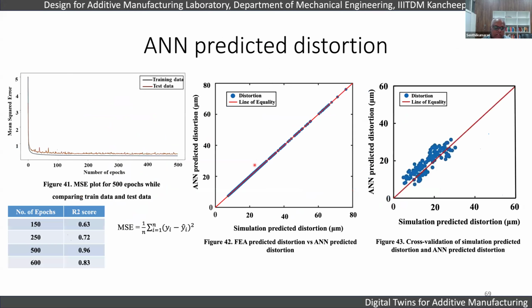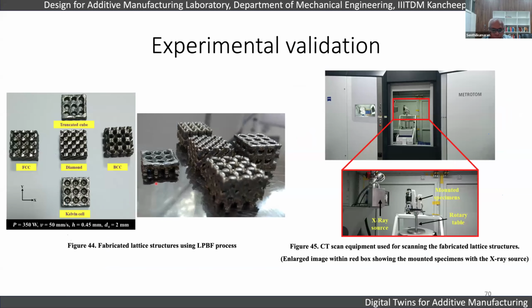You can see that we can get an R square value of as high as 0.96, and we trained for 500 epochs. Then we did an experimental validation with the Inconel material. And to understand how the distortions happened in the interior of the parts, we did a CT scan using computed tomography.